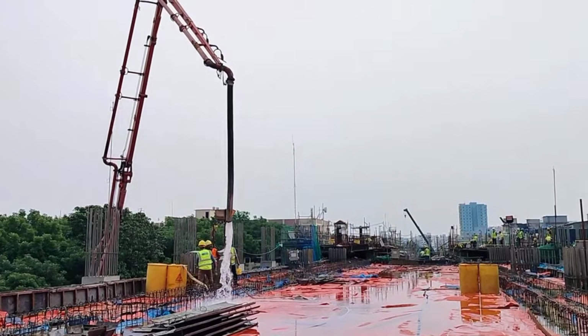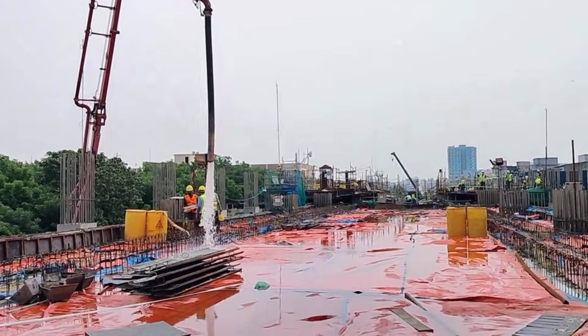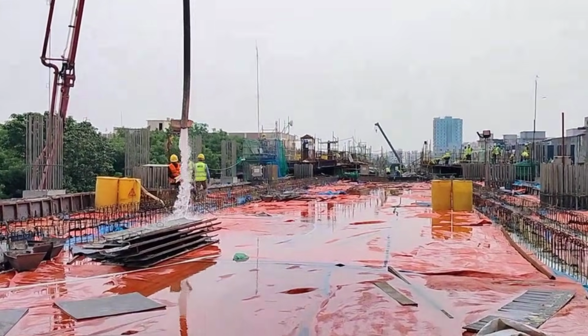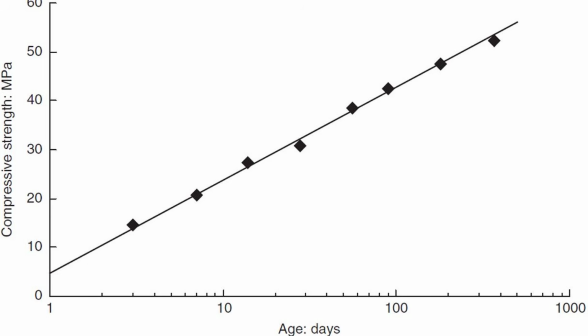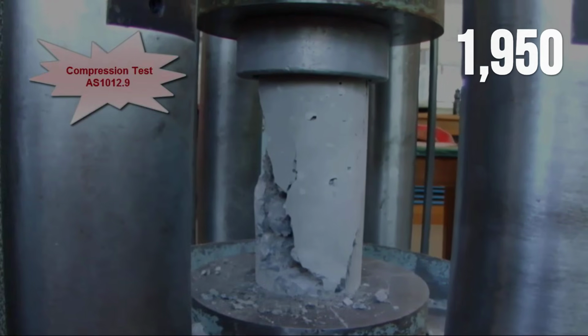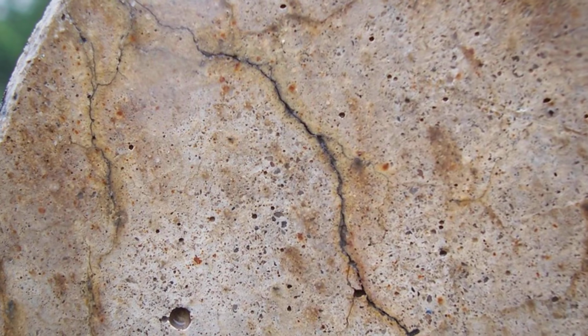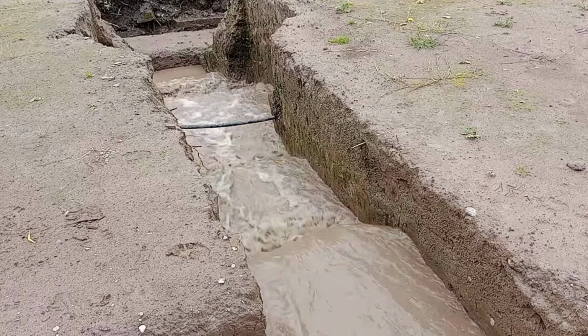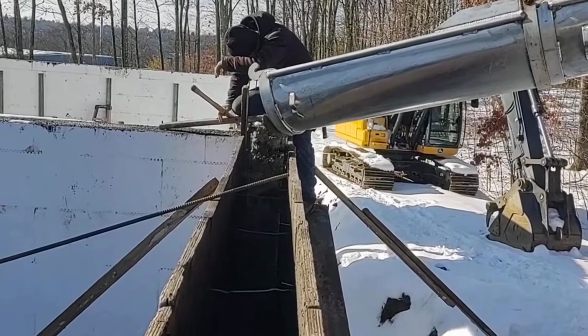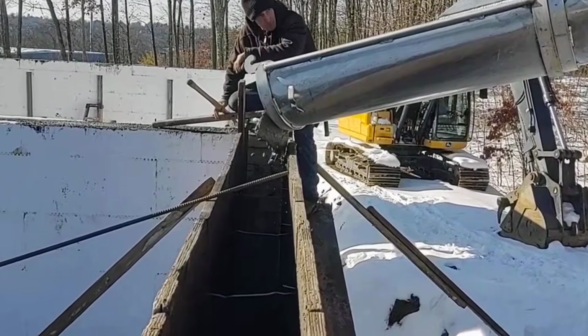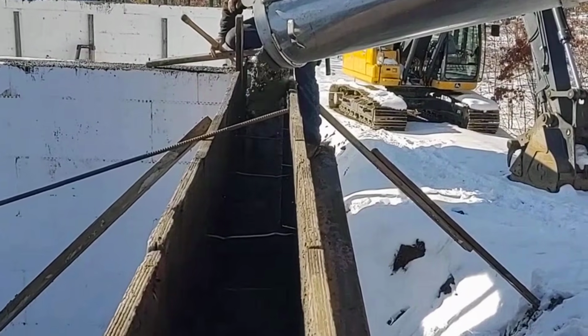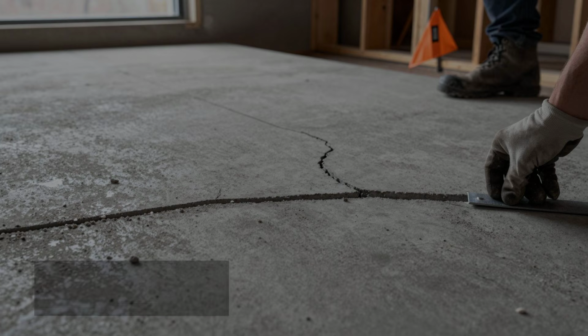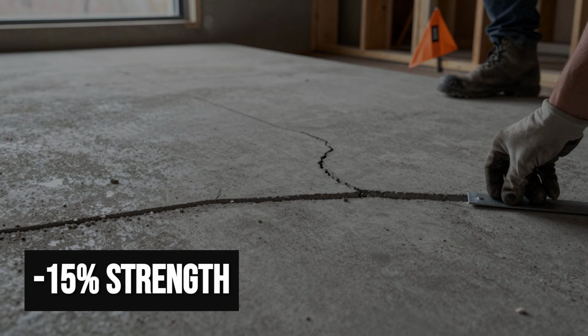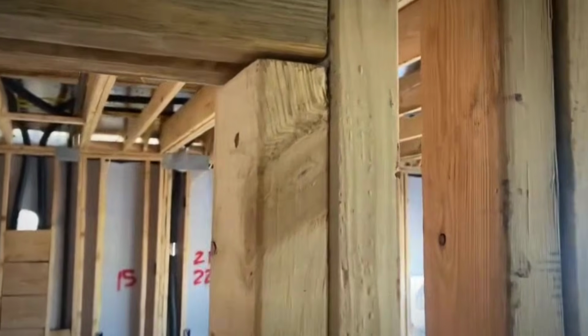Under standard conditions, 20 to 30 degrees Celsius and continuous moisture, the lab curve supports this. A 7-day compressive strength lands between 1,950 and 2,250 pounds per square inch. But the field is not a laboratory. In cold weather, when temperatures fall below 40 degrees Fahrenheit, hydration slows. The penalty is severe. 7-day strength can drop by 10 to 15%, and the 28-day target may be missed entirely.